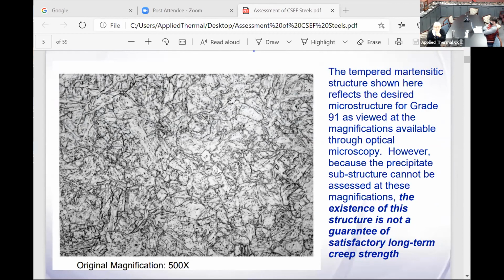This is just showing, again, some repeats of what Dr. Joe is showing, but yeah, this is showing the tempered martensite substructure. The important issue when you're dealing with field assessment inspection is that precipitate substructure cannot be assessed at these magnifications. There is no guarantee that what you see, say from replication, will be a good representation of what is in the material subsurface.